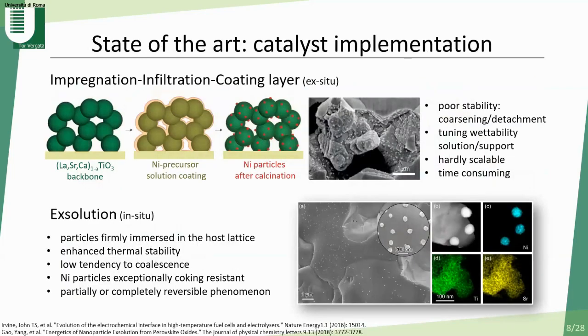To improve the catalytic performance of perovskite oxide as an anodic layer, different techniques can be used, such as infiltration or impregnation of the perovskite backbone with different metals, or coating the perovskite anode with metallic salts. In those cases, the limitation is the coarsening of the metallic particles, and the time-consuming nature of those techniques makes scale up impossible. Thus, the exsolution of metallic nanoparticles from the perovskite structure can solve some of those limitations.